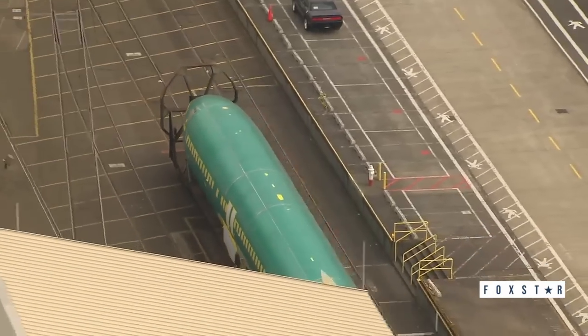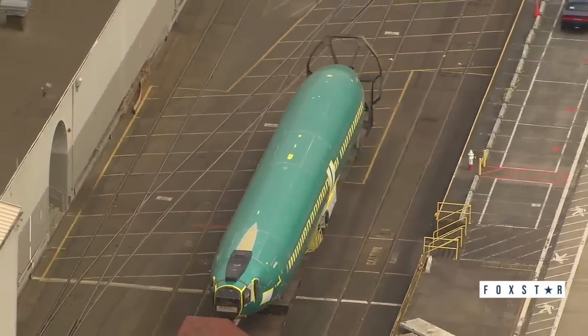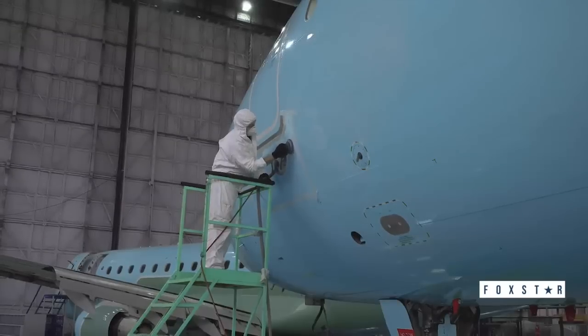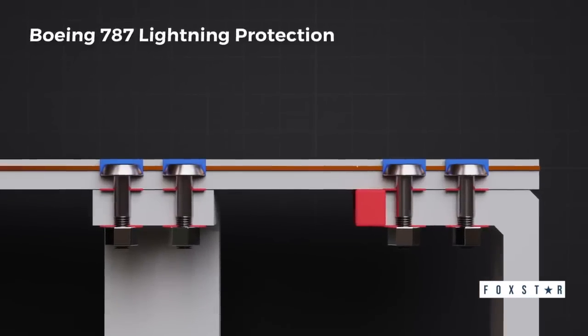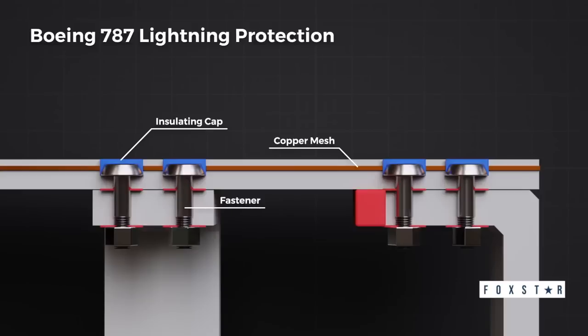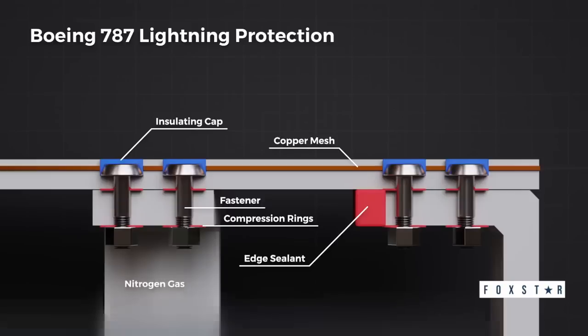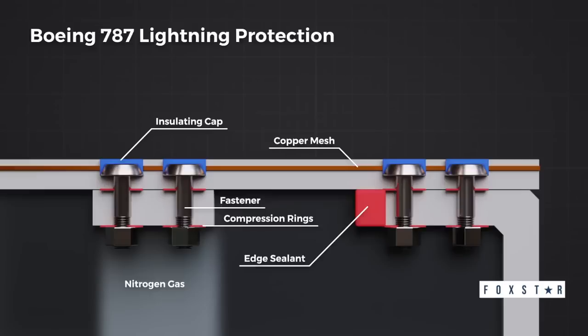Since then, the aviation sector has implemented rigorous safety measures and lightning protection tests to ensure an accident like this could never happen again. Early 787 wings were designed with copper strips to ensure the electrons had a path of low resistance along the surface of the wing, ensuring they wouldn't travel to the fuel tank and cause a spark, while also preventing resistive heating damage to the composite structure. Fasteners were sealed with an insulating material to stop electricity from traveling down the metallic fastener into the fuel tank, and the fasteners themselves were fitted with compression rings and a sealant to eliminate potential spark locations caused by gaps and sharp edges. Finally, the 787 has a nitrogen inerting system that fills the tank with nitrogen. Ignition can't happen without oxygen.